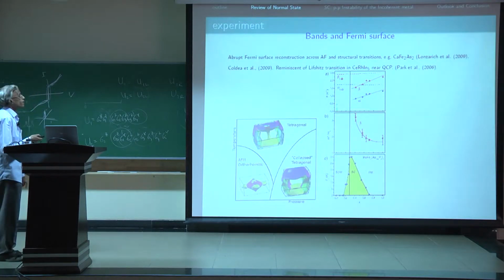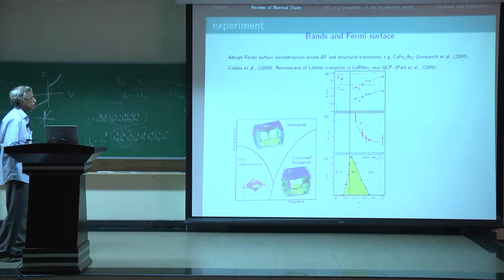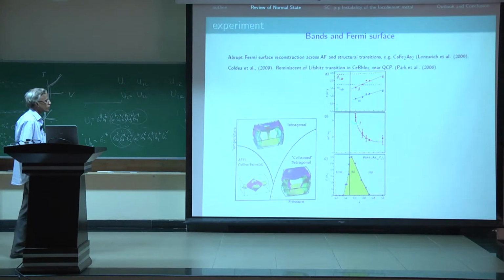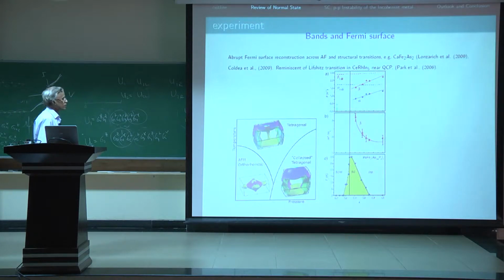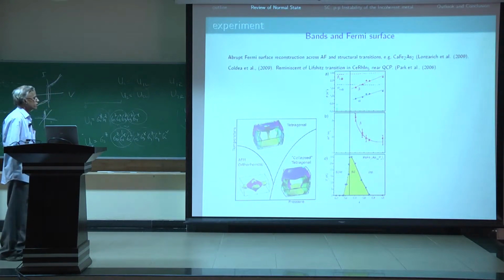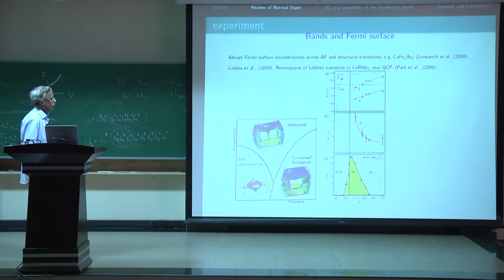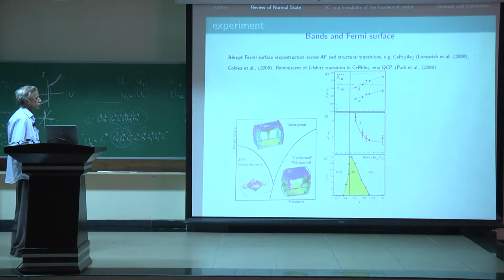So for the 122 iron arsenides, you can see very complicated Fermi surfaces. In the tetragonal phase, you have this central pocket which is appreciably warped along the c-axis, and so are the hole pockets at the corners of the Brillouin zone. In the collapsed tetragonal state, this is drastically modified, as well as when one undergoes a transition from the tetragonal to the orthorhombic state, followed by antiferromagnetic ordering, which always occurs in the orthorhombic state.